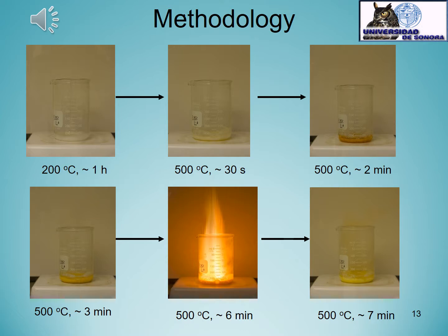After the evaporation process, we increase the temperature up to 500 degrees, and after around 7 or 10 minutes we can observe the solution combustion product, which is a powder. Previously to the formation of this solid, we can observe the mentioned flame and this fumes emission. All of this process we carried out on the fume hood in terms of security.